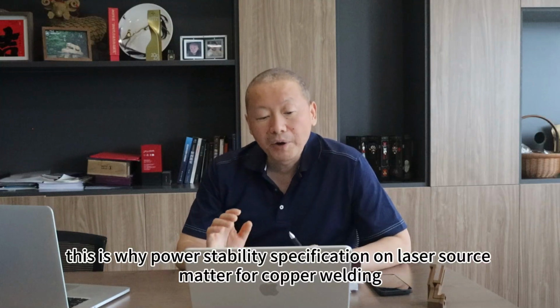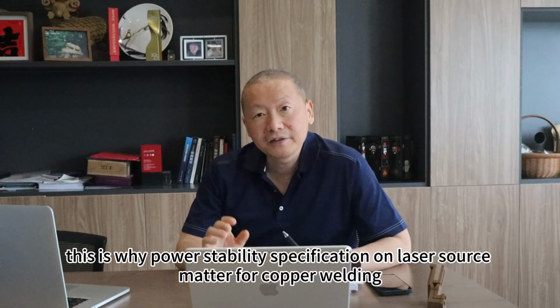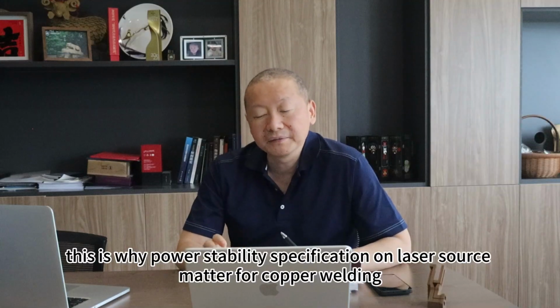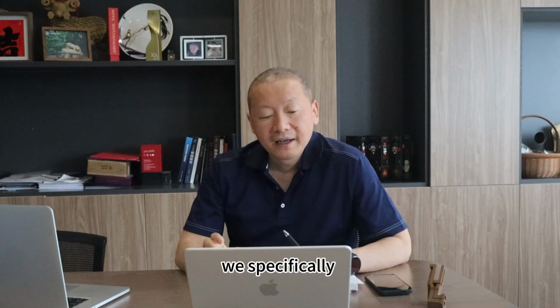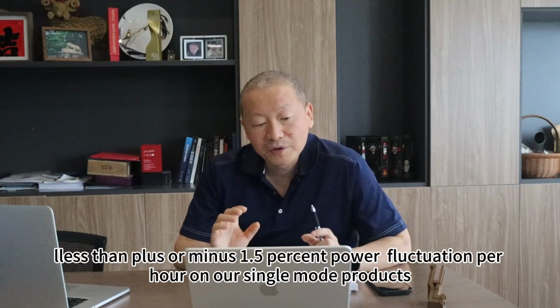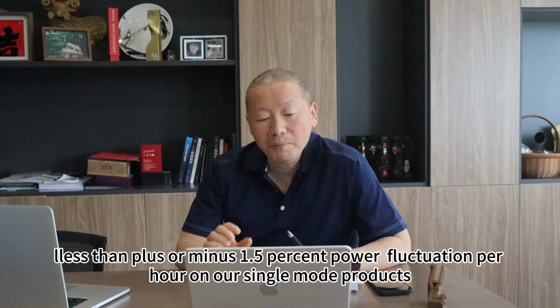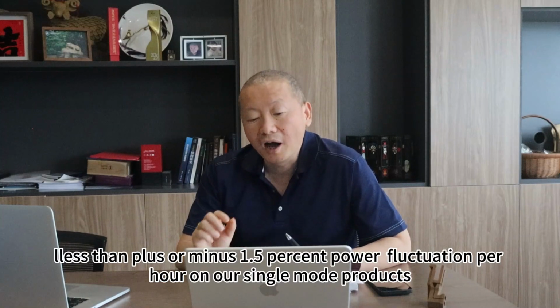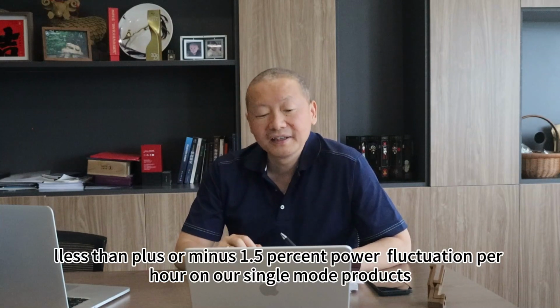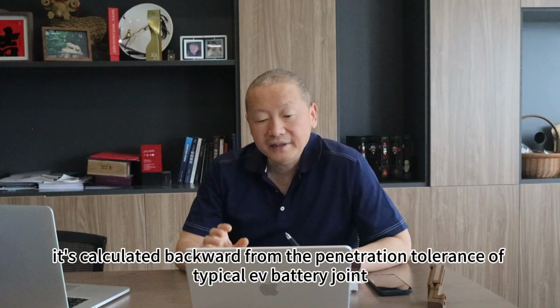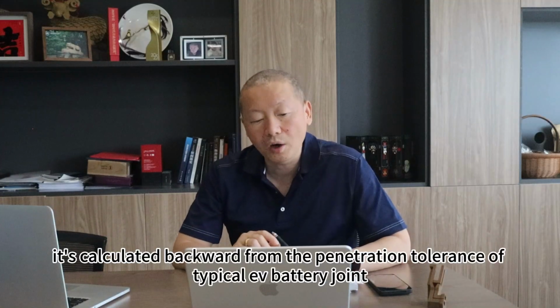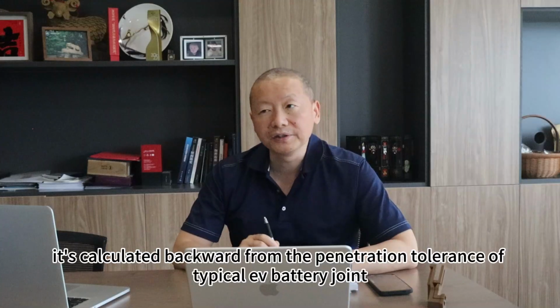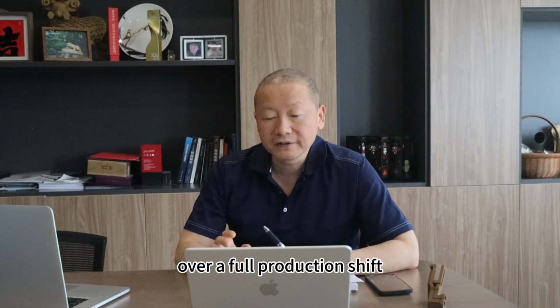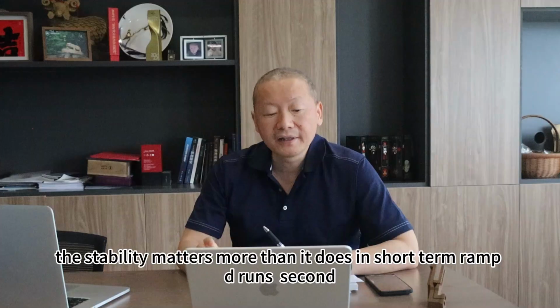This is why power stability specification on a laser source matters for copper welding. We specifically specify less than plus or minus 1.5% power fluctuation per hour on our single mode product. That's not arbitrary. It's calculated backward from the penetration tolerance on a typical EV battery joint. Over a full production shift, the stability matters more than it does in short-term R&D runs.